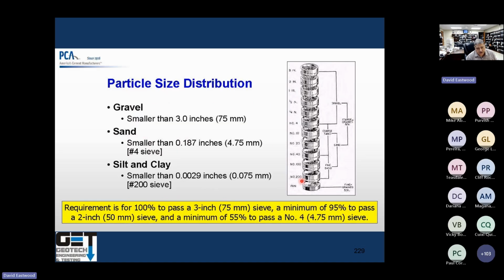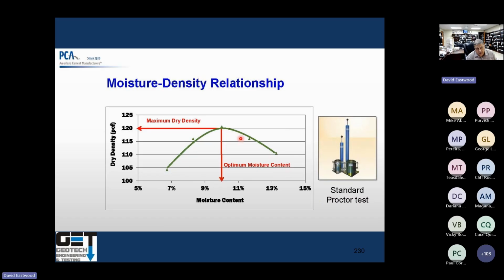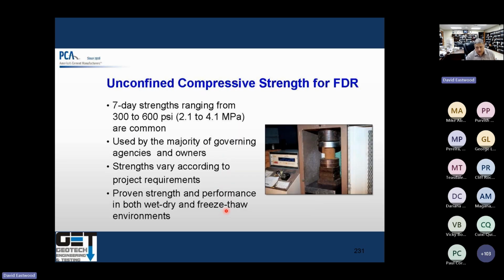Make sure after you pulverize this stuff, 100% passes the 3 inch, minimum 95% passes the 2 inch, and 55% should pass the number 4 sieve for the gradation of the pulverized material. This is your Proctor curve. You get them all mixed up and you compact them. You get a maximum dry density of 120 at a moisture of about 10. Also, the material mixed with cement should have a 7-day strength of about 300 to 600 psi. Majority of the states, like TxDOT, use some kind of strength values with the project requirements, proven strength and performance in both wet and freeze-thaw environments.